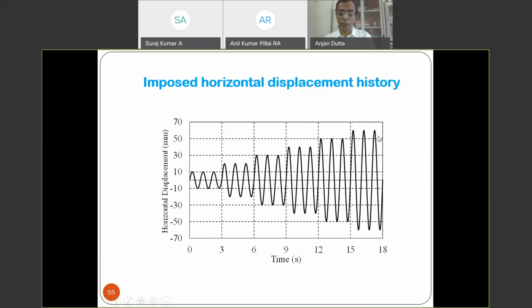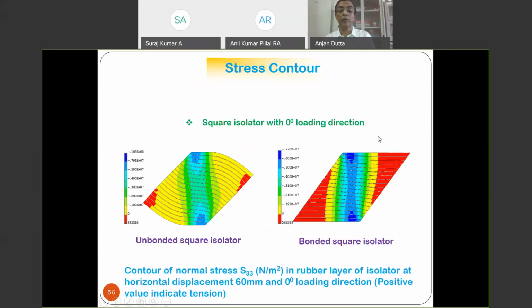Slowly, we have increased the displacement range. And this is what you can see now. So in the numerical simulation, I can have anything. I have used one which is connected to the superstructure and substructure, and I have used another one which is unconnected. The one which is not connected, you can see what we call a rollover deformation. Now, what is happening? If the rollover deformation is like this, it is actually in contact with only this flat surface. So thereby, the actual transmissibility of the vibration from the substructure to the superstructure gets substantially reduced.